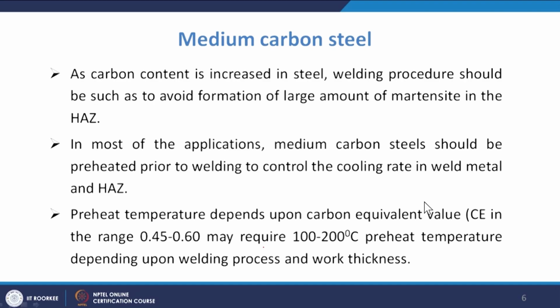Okay. Similarly, medium carbon steel has moderate weldability. As carbon content is increased in the steel, welding procedures should be such as to avoid the formation of a large amount of martensite in the HAZ. So why it is moderate is that the main problem is higher carbon content means higher carbon equivalent percentage, so hardenability increases, that means martensitic formation is much higher. So we have to provide a certain environment so that we can reduce the formation of martensite.